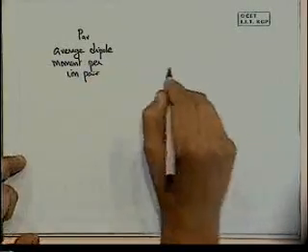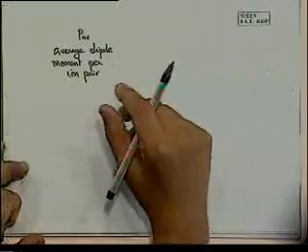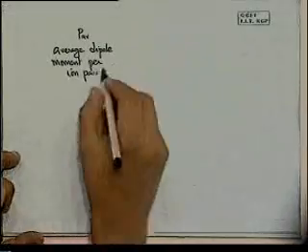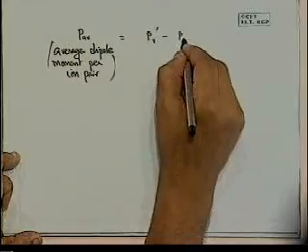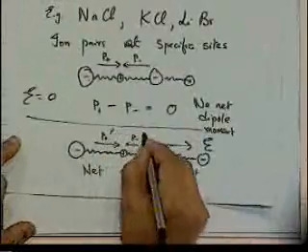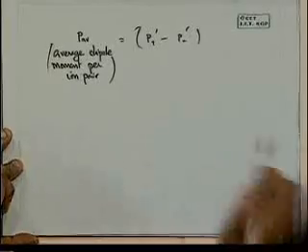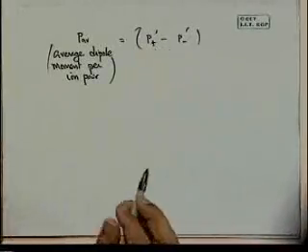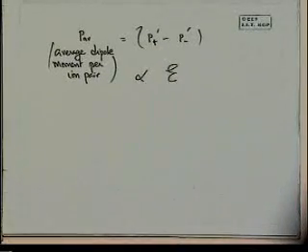Remember, in the case of electronic polarization, the shift is all within each atom, and so the number of atoms or number of molecules would give us the correct answer. Here we are talking per ion pair. It's simply now some other value. I don't remember if I put the notation dash, to indicate that it's a different value from the previous case, and we have a net value. And all we'll say at this point is that it's proportional to the applied field. You increase the applied field, we will get a larger net dipole moment.